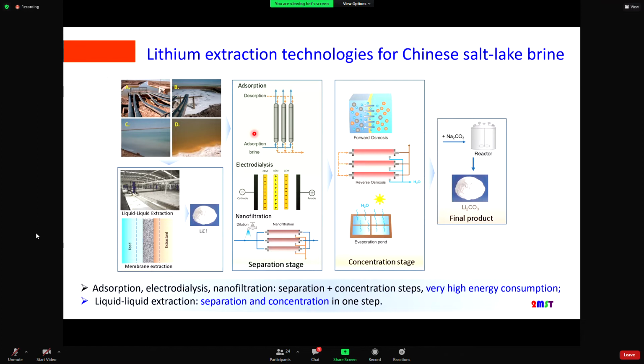The first is adsorption, electrodialysis, nanofiltration—this is to separate magnesium and lithium. But afterwards, we have the lithium-enriched brine, which still has very low lithium concentration. RO is used to further concentrate this lithium. Even RO is not able to reach the lithium concentration of 3% needed to precipitate with sodium carbonate to produce lithium carbonate. So evaporation pond has been used—that's the practice. Recently, we proposed forward osmosis, but unfortunately, the forward osmosis membrane is still under development.